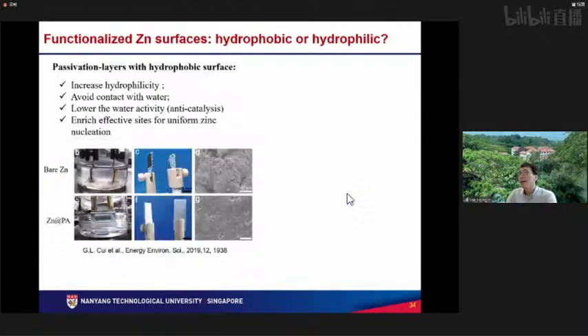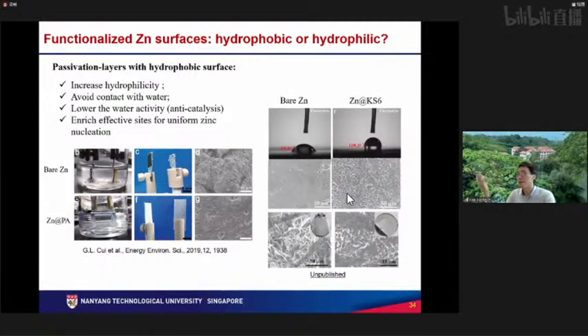Okay, but the problem, for example, this is the work by Professor Cui Guanglei in Qingdao. They coat the surface with this polyamide, PA, which is a polymer layer. They say that this PA makes the surface more wettable and suppresses the corrosion problems. Okay, but actually, we also tried to do something similar.